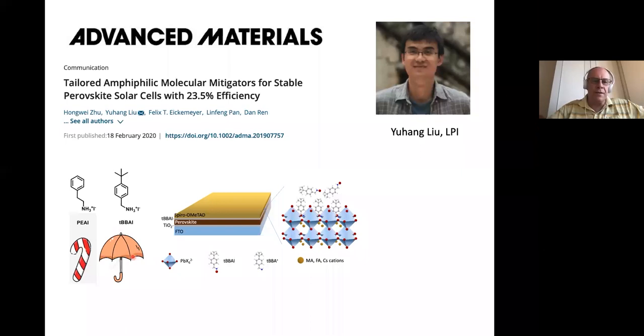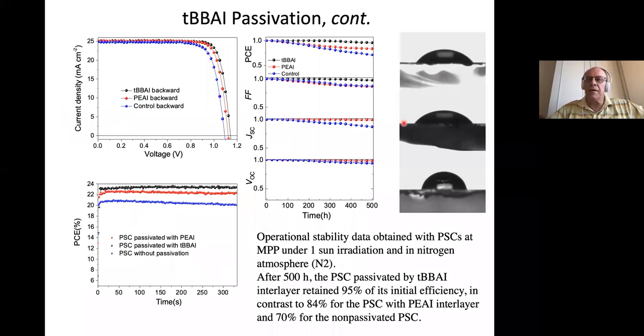So if we look into contact angle measurements, this is without any passivation. This is with the phenylethyl. And this, as you see, you increase the contact angle to a hydrophobic surface, which also makes it more resistant towards humidity. And we got our best stability device with this tBBAI passivation molecule. After 500 hours, 95% left. This is not the high temperature measurement. And also the efficiency is higher with this passivation molecule.